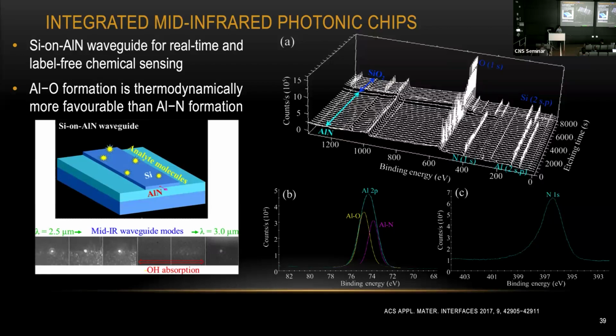But before you go and do a measurement, the long depth profiling, we need to etch through the entire silicon waveguide and aluminum nitride here in order to see the interface between the aluminum nitride thin film and the silicon substrate underneath. As far as I remember, this etching took almost 24 hours. It's almost 120 nanometer thick. So we need to go through multiple layers and finally get to the interface layer here.